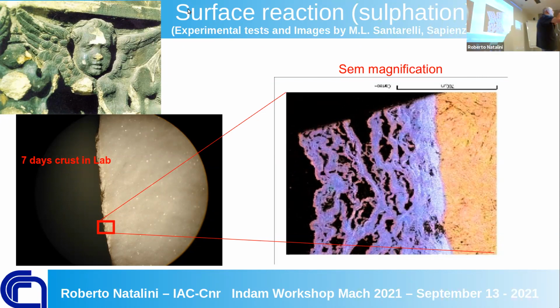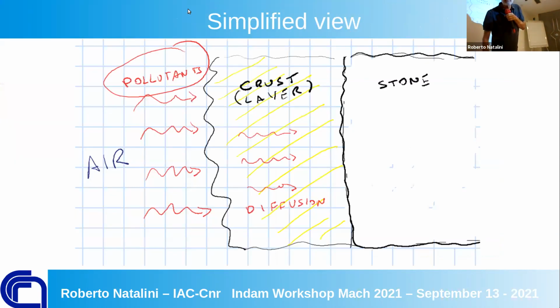But the idea is that all other models for other kinds of crust, other kinds of interaction, you can build by the same approach. I mean, here I described what we did, but the same model can be adapted to different situations. So the simplified view: we have air with pollutions, and here we have a crust, some external layer. Maybe, for instance, as I anticipated, for metals we have 2 layers of different materials. And here we have the stone, the pristine material, which is at the end. And so you have diffusion inside and then the reaction here when you get the new material. And this crust maybe is a mixing of different components. Maybe it's not pure gypsum or pure crust, but there are still elements of the original stone.